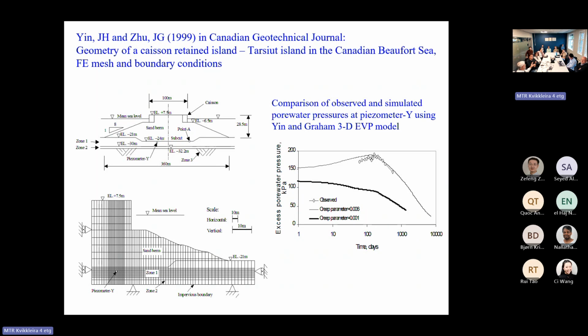If you don't believe me, you can do a simple triaxial test, do the consolidation. You close the valve, and you can measure the pore pressure on the top or bottom, it doesn't matter. The pore pressure will increase. So creep is an independent mechanism which can cause the excess pore pressure increase. This is what I say.